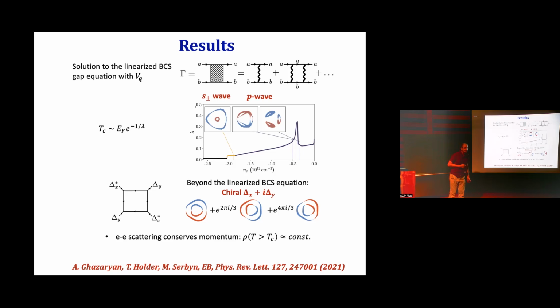Is it an experimental fact that time reversal symmetry is being broken by the superconducting state? No, that's not the experiment. In helium-3, you also have similar triplet pairing and p plus ip. But unlike helium-3, here you have valleys. Exactly. So what are some differences with helium-3? The phase that you get here is topologically different from the phase that you get in helium-3. That's one difference. The other difference is that because you have the valleys, the state can be either singlet or triplet. And what we believe is happening is that in one of these two superconducting phases that was found, it decides to be singlet, and in the other one it decides to be triplet. It's not the same symmetry of the order parameter, but of course it's related.